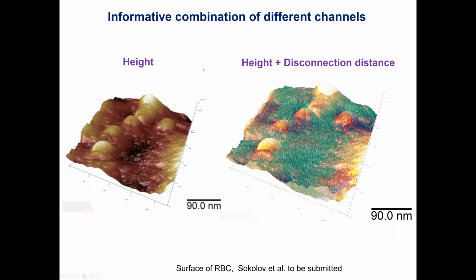So this is just to give you a flavor of how multiple channels can be connected, even if you have height and disconnection distance. This is a red blood cell infected with malaria parasite. These bumps are where this parasite tried to escape. And you see this, if you put disconnection distance, which is the size of the glycocalyx molecules essentially attached to the cell membrane, you can see these bumps are bald. So there are no molecules attached to it, while the actual cell is covered with those molecules. This is just, again, we are yet to understand this, and right now it's in the process of writing the manuscript.